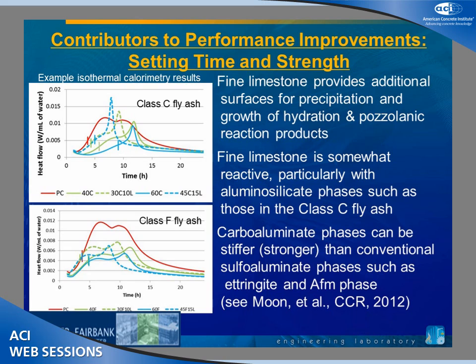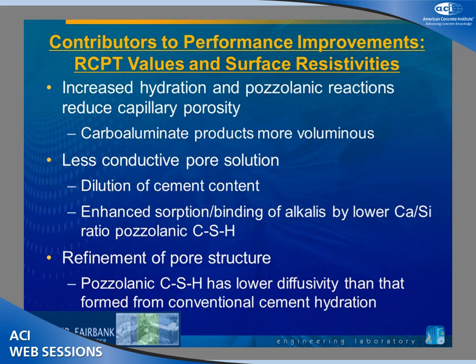The limestone does participate in the reactions and form some carboaluminate phases, and Moon and his group in California have shown that those phases can actually be stiffer than ettringite or sulfoaluminates. So that could be another reason to get increased strength. When you look at durability, the limestone's accelerating the reaction. You have more hydration. The carboaluminates take up more space, so you're cutting down your porosity.